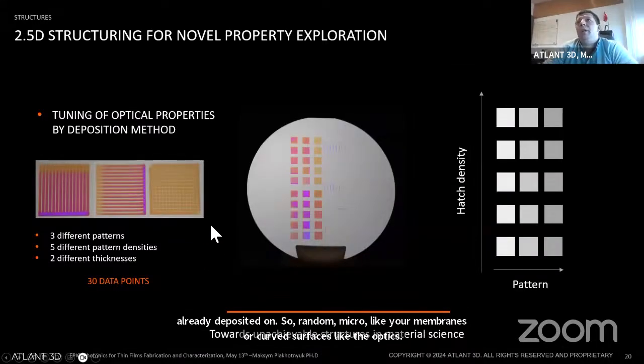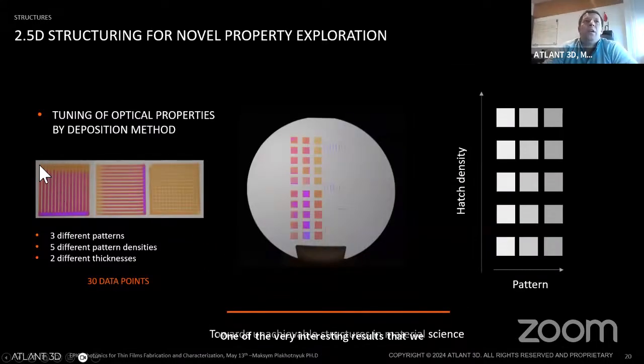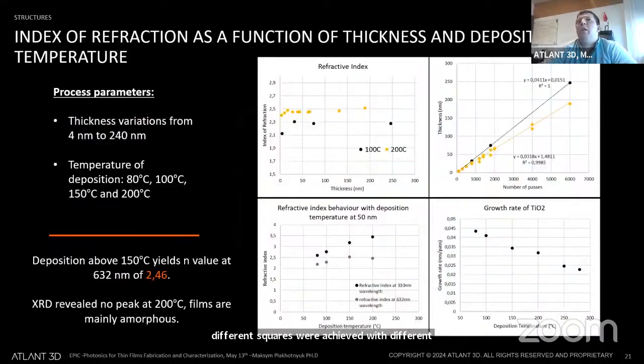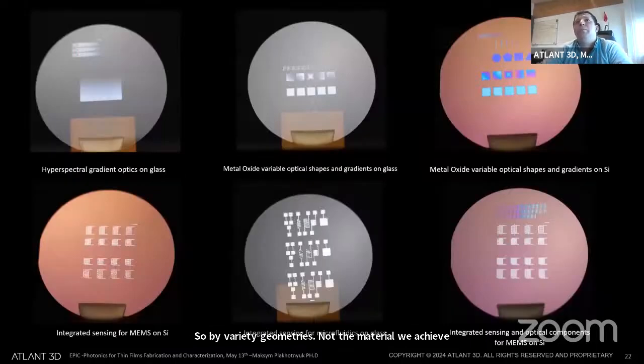One of the very interesting results that we recently obtained is by printing variable vertical, horizontal lines, we obtained squares, as you could see here. And by varying different thicknesses, you could see different squares were achieved with different geometries. And the next, what we did, we tested this to basically modulate refractive index. So by varying geometries, not the material, we achieve different refractive index changes. So this is just an overview to give you an idea what we did recently.